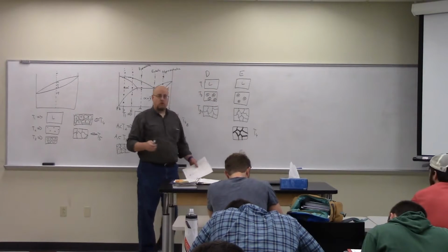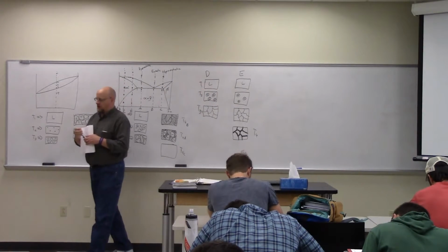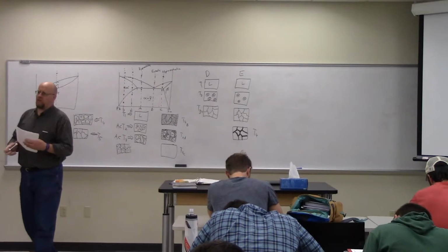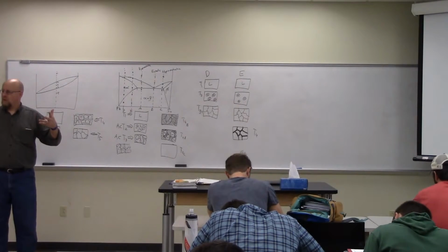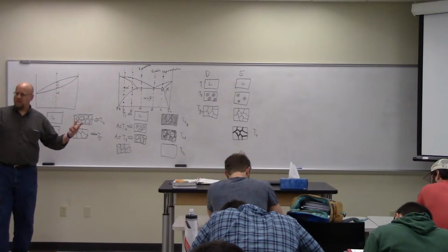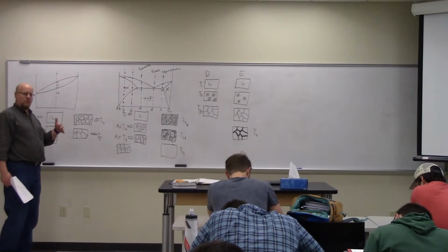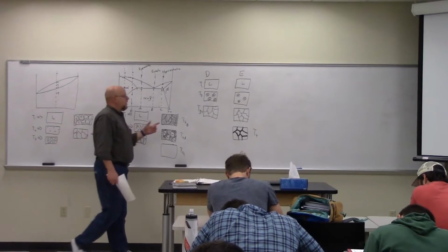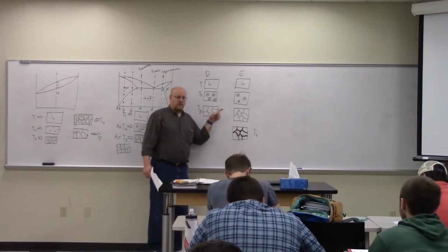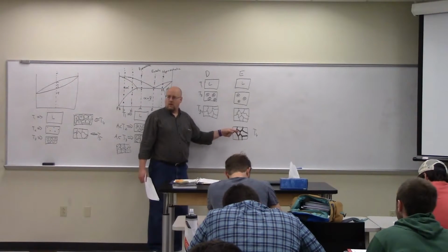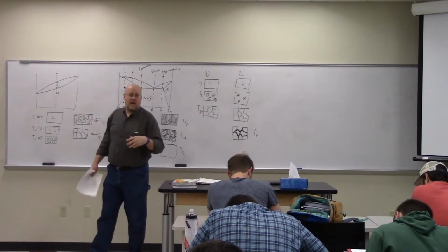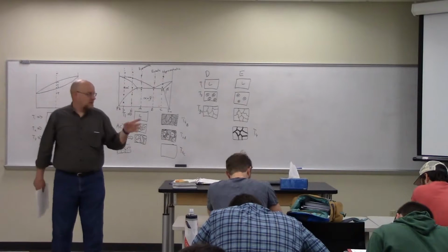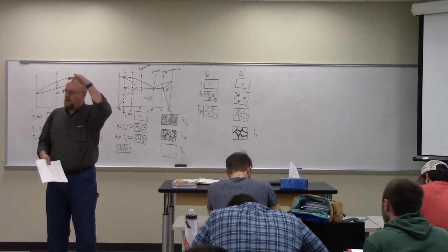We could get better diffusion there. But I said typically grain boundaries represent such a small fraction of the cross-section that we don't take that into account. The energy barrier for diffusion at the grain boundary is smaller. But in this case, since I have to form some beta here, the beta is going to most readily form at the grain boundary areas where there's disorder among the atoms, and the tin atoms can coalesce and form beta material.